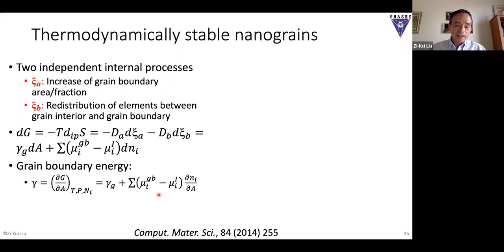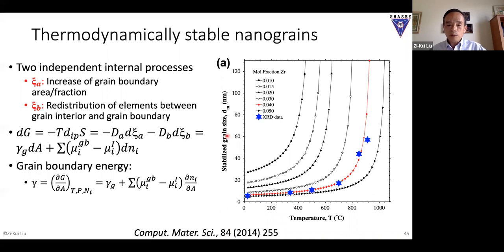So here's what happens next. In 2014, we got some work with the Army Research Lab. They asked us to do this modeling, so we did. We took one binary alloy, iron-zirconium, which had experiments done. We did different compositions, different zirconium concentrations, to stabilize the grain size - meaning the grain boundary energy gamma is zero, so no driving force for grain growth anymore, as a function of temperature.